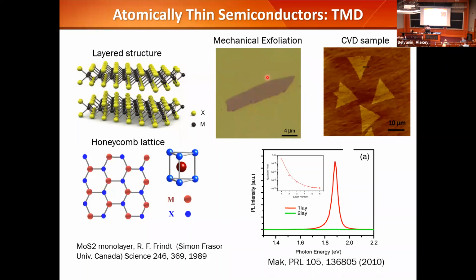Right. So these materials within a single layer are covalently bonded, but between the layers, every 3 atoms thickness is 1 layer, and between the layers they have van der Waals bonding. So in fact, to give people due credit, the MoS2 monolayer was isolated long ago, not starting with the Nobel laureates, in fact, right? And published in a decent journal.